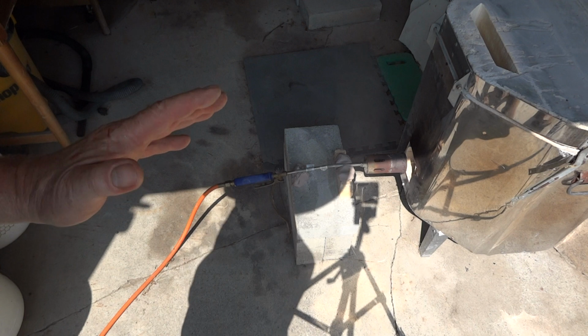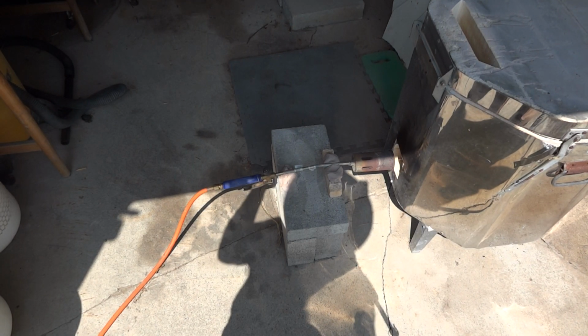And you just light it, and then you want to keep it on a very low flame for probably the first hour and a half, even 2 hours. Just keep it real low, and then just start gradually turning it up. I'll be keeping a kiln log, and I'll be checking in with this through the day. But for now, this morning, I don't know what the time is, 10:30, 11 o'clock this morning. Probably won't do much until lunchtime, and then I'll be turning it up, and then probably starting reduction, come the end of the afternoon, and probably finish by about 10 o'clock tonight. I will check in with you in relation to the opening of the kiln, so you can see hopefully the good results.